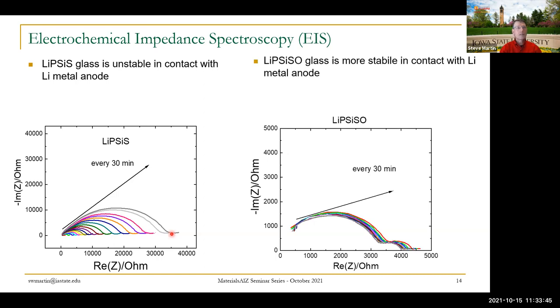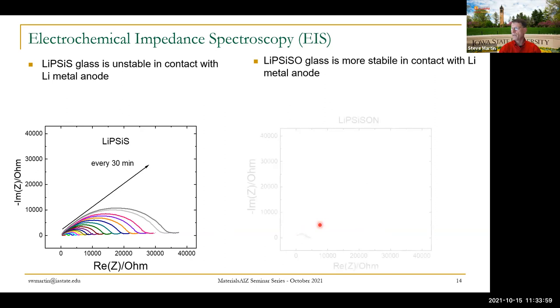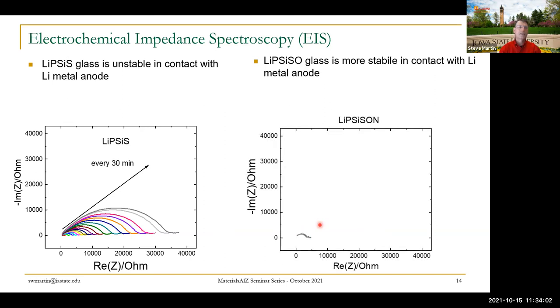The oxysulfide is a lot better. The impedance is high, about 4,000 rather than a couple hundred here. But you see it's relatively stable. It still grows a little bit, but it's much more stable than the pure sulfide. And then you might imagine our pure oxysulfide, this is the data I showed you in the preamble of the talk. This is completely stable and very low impedance over a very long time. These are multiple hours runs, meaning that our glass does what we want it to do, just stay stable in contact with that lithium metal interface.